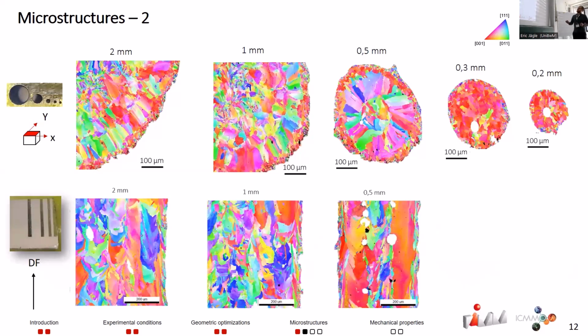When you compare it to the longitudinal cross section, it's really close to what we just saw in the previous presentation. You can see here the little grains on the border for the outer ring, the inner ring, and the hatching zone in the middle.